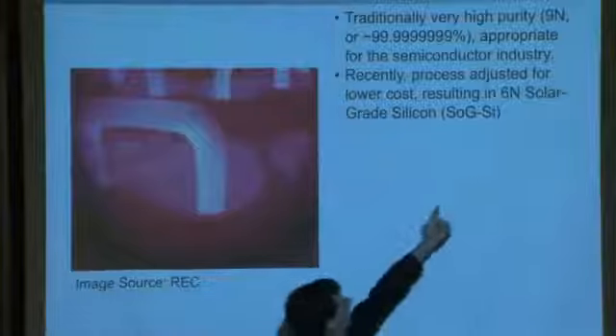The polysilicon production, this is a Siemens reactor. It's much smaller in comparison to the metallurgical grade silicon furnace, much smaller than the carbothermic reduction furnace. Here we have a small human, or a human next to the small contraption. Here are a series of them lined up, almost like little pods. And inside of the furnace, you have these rods that are passing current and heating up, and the silicon is cracking onto the rods. So we wind up with 6 nines, usually called 6N solar grade silicon as a result of this process. We could also go up to even 9 nines using the Siemens process. It can be very, very pure, depending on how fast you grow, what the purity of your silane gas is.